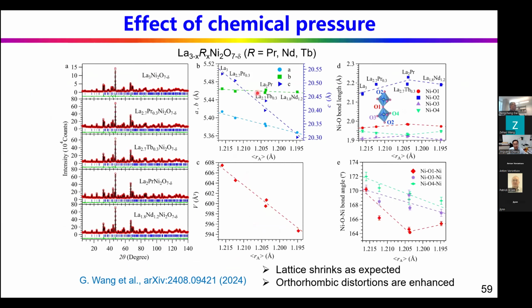So basically, we prepared a series of these rare earth doped polycrystal samples. We started by studying the structure at ambient pressure using neutron diffraction. With reducing the size of the rare earth, the lattice parameter and the volume decrease, and also the nickel oxygen bond length and nickel oxygen nickel bond angle decrease. This is understandable because when you reduce the size of the A-site cations, the structural distortion becomes stronger, so the orthorhombic distortion becomes stronger.